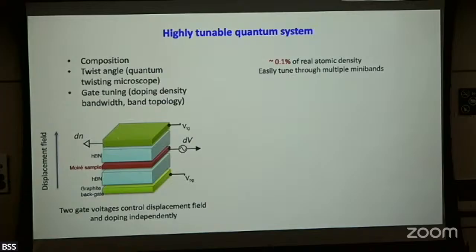But on top of that, I'm going to add an oscillating small AC voltage to my sample and try to see what is the current charge density collected or induced by this AC voltage. So if you look at this ratio, you are just looking at, for this much energy change, how much density you are going to induce, right? So this basically is measuring density of states.